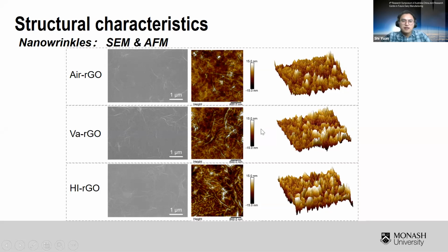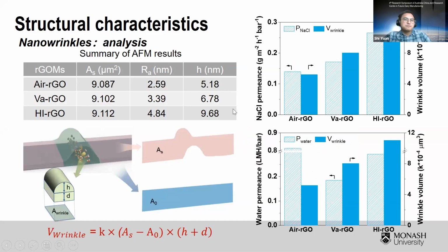We then further analyze the AFM results and got the surface roughness and surface area, which are the indicators of the nano wrinkle size and the density respectively. And we also developed a model to calculate the wrinkle volume. And we can see from this figure, the Air-rGO shows the smallest wrinkle volume.